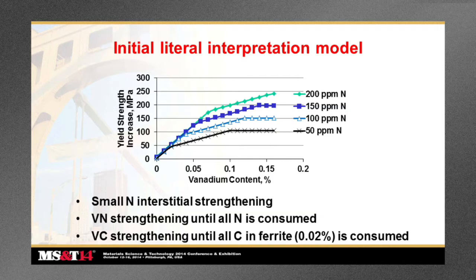but what it does show is that as you add the vanadium, there's ample nitrogen to combine up until the point you reach the stoichiometric level of vanadium to nitrogen in the system. So vanadium nitrogen strengthening occurs at the highest rate. The rate of strengthening, as you see, is the steepest slope. But eventually, you do run out of nitrogen. And that vanadium nitrogen ratio stoichiometrically is about 3.68 to 1. We use about a 4 to 1 rule of thumb for that design.